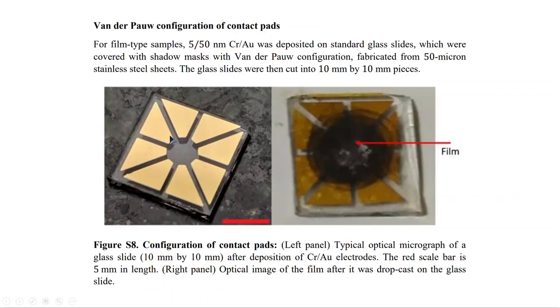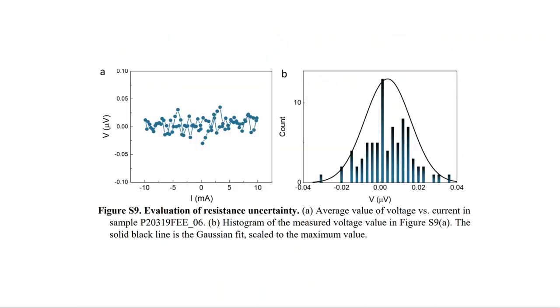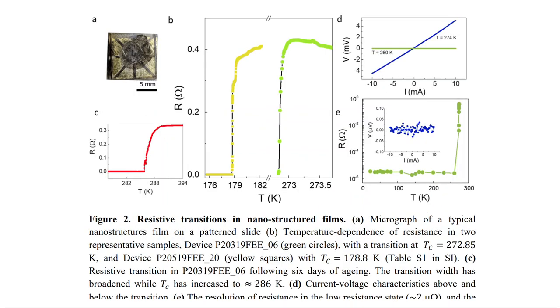In particular, what they do is basically put the film down on this system that has 8 contacts, and then they can measure currents and voltages between any of the 8 contacts. And they also report the voltage sensitivity for which they can measure when they measure the voltage. This is the sensitivity. It's in the order of 25 nanovolts. So they're able to resolve very small voltages, which is a good thing.